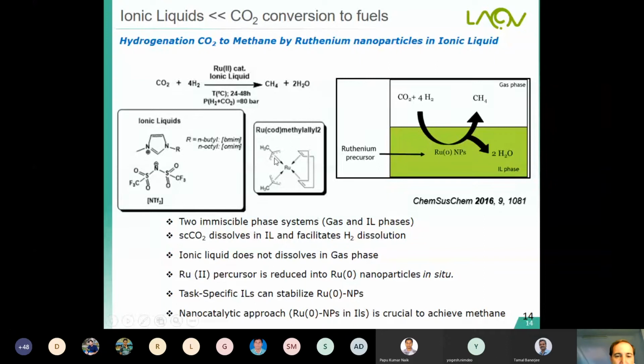This is a homogeneous solution in the beginning, and then we have the formation of ruthenium nanoparticles in situ during the reaction. It means we have two immiscible phase systems, the gas and ionic liquid phase. The supercritical CO2 that I mentioned in the beginning, we can combine with ionic liquid because supercritical CO2 can solubilize hydrogen and facilitate hydrogen dissolution. Ionic liquid does not dissolve in the gas phase. We can have the formation of ruthenium(0) nanoparticles in situ, and this is crucial to form methane.